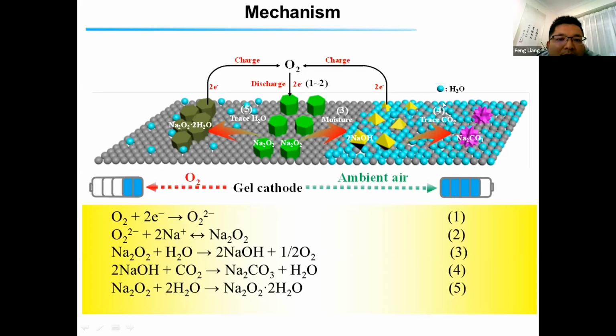But in the case of ambient air, as we know, in real air the humidity is very high. So in this case, the sodium peroxide reacts with the moisture and then forms sodium hydroxide. In the case of sodium hydroxide, it has a high ionic conductivity. Also, it is soluble, so it is just on the surface of the electrolyte. Therefore, in this case, the battery has better performance than the sodium oxygen battery.